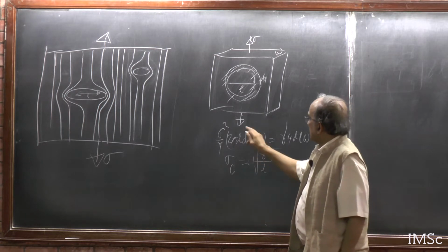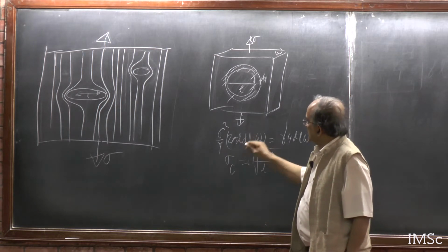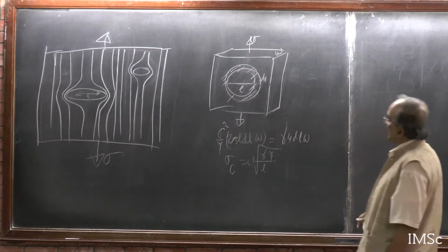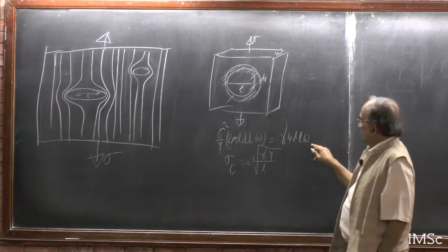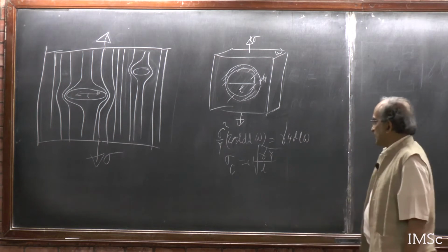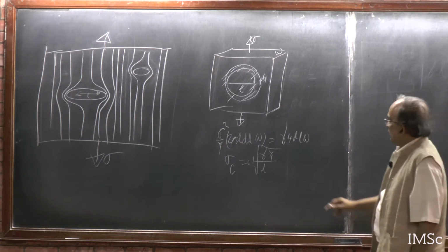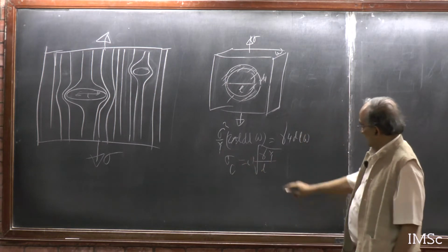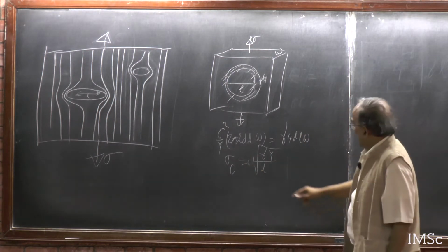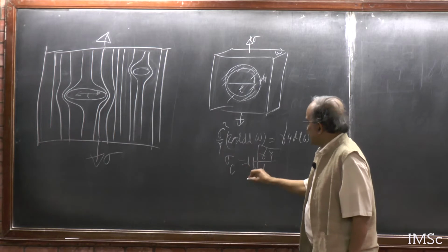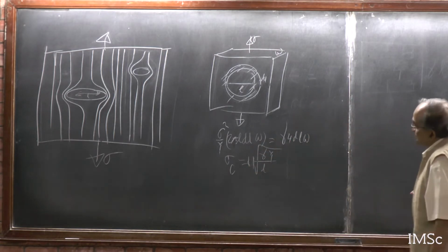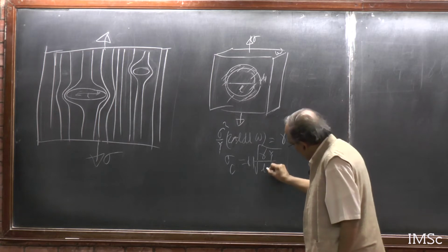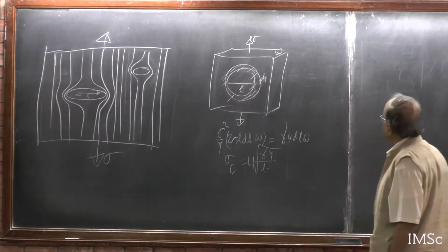Because typically energy density is, and the density volume is L to the D, and this will be L to the D minus 1, so that would be always L left, and surface energy density and linear elasticity modulus will be there, and this would be the form. The prefactor may depend on the geometry that you assume or you find appropriate. So in terms of scaling, this will remain like this.